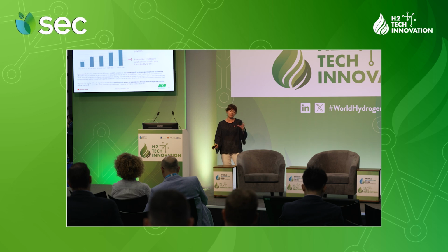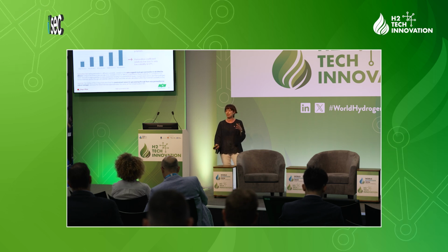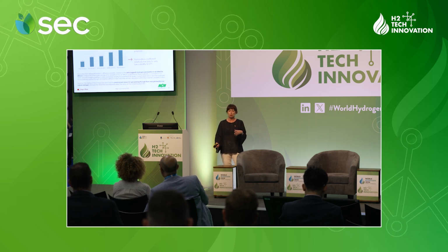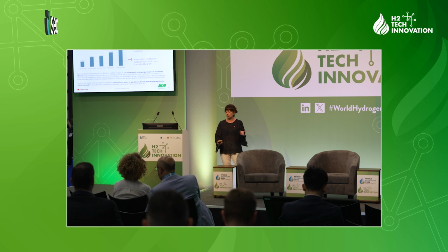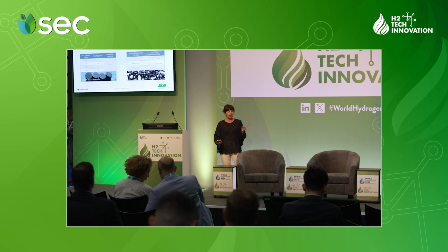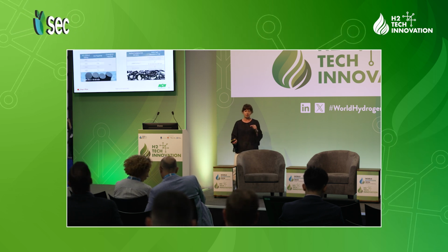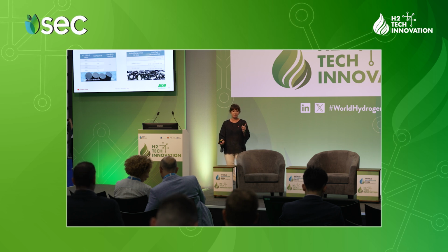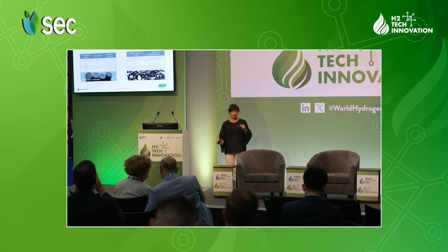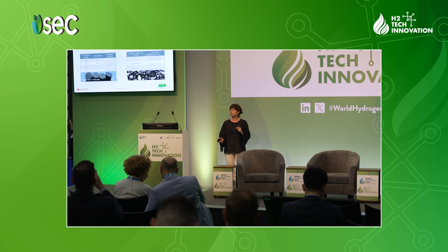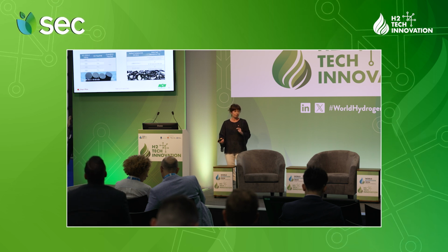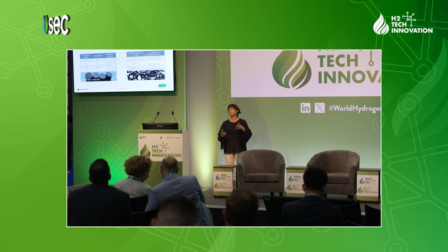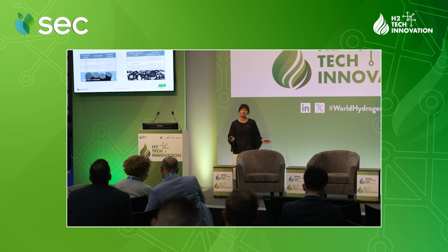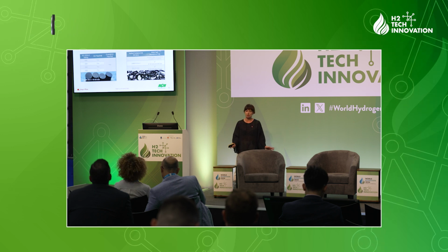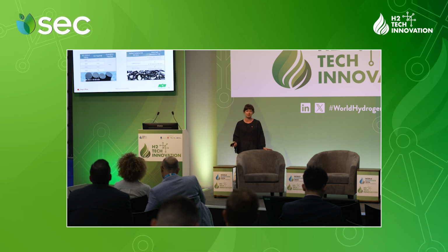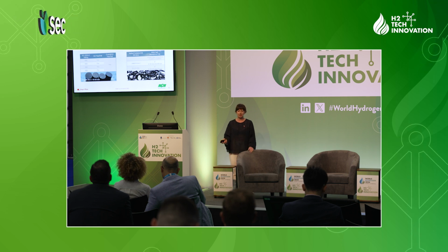This suggests that the predominant reason for the gas leakage was permeation, so natural leakage. On selected materials, we then ran some rapid gas decompression testing at different pressures, HNBR and FKM, with very good results in general, suggesting that possibly rapid gas decompression may not be a big issue in the case of hydrogen gas, in contrast with other kinds of gases.